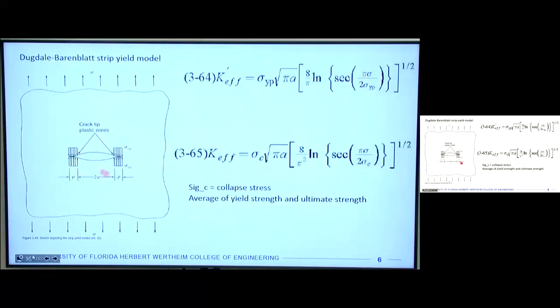So what I'm going to do is a bunch of experiments, with a bunch of different geometries here, and taking maybe a bunch of different distances here over which that occurs, and I'll come up with an effective fracture toughness. So K prime effective is going to be a function of the yield stress and the same term that we had before, square root pi a, and then it's going to have a bunch of geometric terms that are dependent on the stress that's being applied compared to the yield strength. So there's a sigma here, and then there's a sigma yp here. Okay, so we're assuming that this stress is less than the yield strength. So that fraction, we take the secant, the natural log, bunch of coefficients, square root of that, multiply it by this to get some effective fracture toughness.